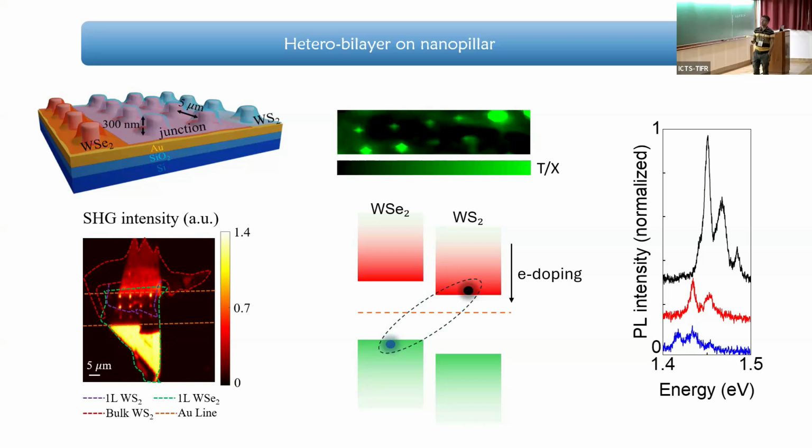The second thing is that we talked about the funneling. It's not just the change in the band gap. I've not done these calculations, but there are reports from DFT calculations which show that it's the conduction band that actually bends, while the valence band more or less remains flat. So if you excite with, let's say, an off-resonant laser, a lot of electrons will also funnel, not so much the holes.